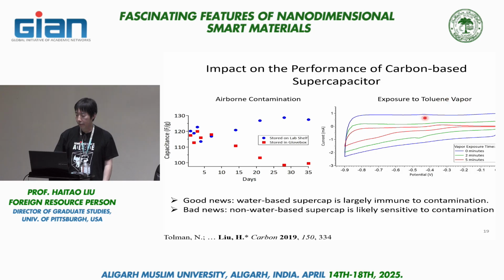Okay. We also made model supercaps. We're not very good at doing this, but we made some very simple devices and looked at how toluene vapor can impact the device performance. And here, there's no surprise. Exposing the device to toluene vapor, while exposing the carbon material to toluene vapor, greatly reduced the ion storage capability. And this is clearly shown in this charge and discharging curve.